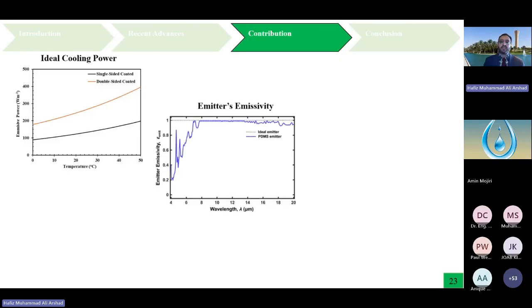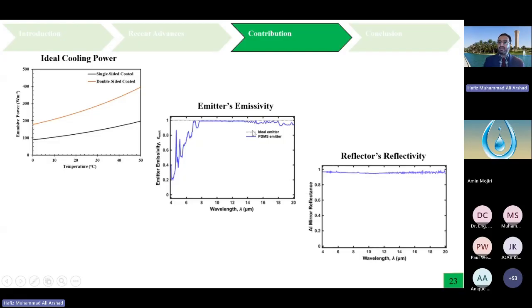And when we compare the emissivity of PDMS with an ideal emitter, you see that within the atmospheric window, which is from 8 to 13 micrometer, the emissivity is actually near to the ideal emitter. The reflectance of the aluminium mirror that we used was very high, reaching up to 0.9.